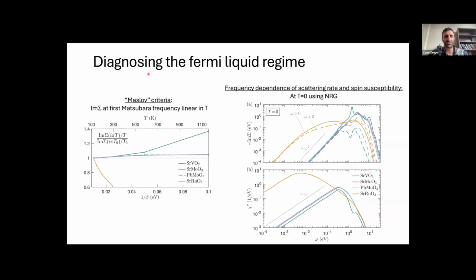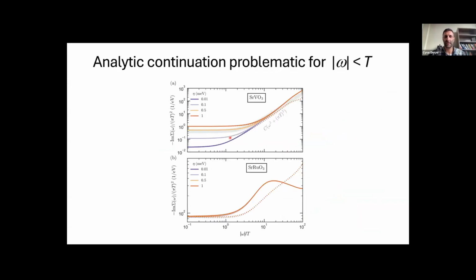But as I was saying, we have many other ways of diagnosing that we are in the Fermi-Liquid regime, and we can safely use the Fermi-Liquid scaling to extract parameters, including the so-called Maslov criteria on the first Matsubara frequency, that it should be linear in T, and also looking at the scaling of the scattering rate as well as the spin susceptibility at temperature equals zero, which can be done via NRG calculations. So I won't go into any details of this, but we can have plenty of confidence for the materials that we're looking at that we are in the Fermi-Liquid regime, and we expect Fermi-Liquid scaling.